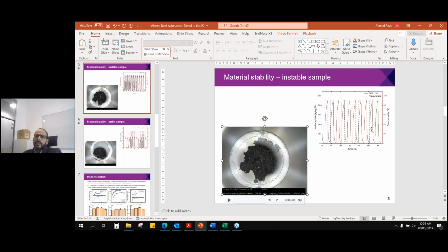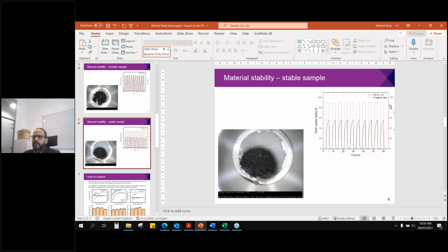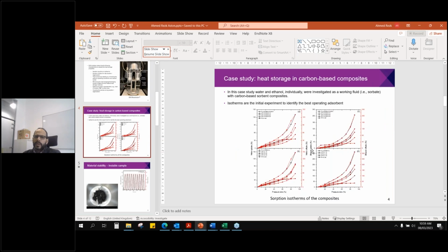Although the stability curves here show a very good trend and there is no degradation in the absorption-desorption behavior between the extremes, still the material is not applicable. We compare it with 10% concentration, for example; 10% is better. However, when we look here, the 10% is low in terms of the endotherm. So if we look at the practicality of the material, we might go for 10%, not the high concentration of 30%, which achieves a high absorption rate.